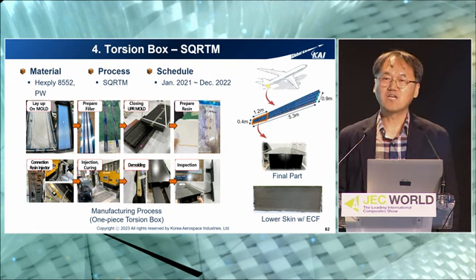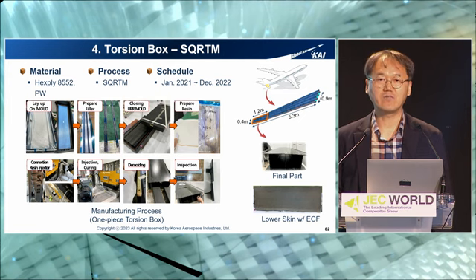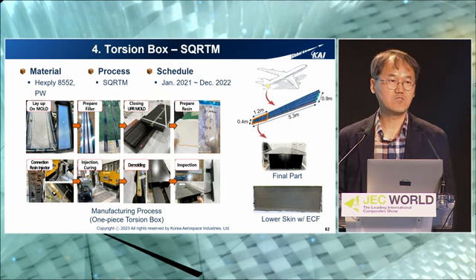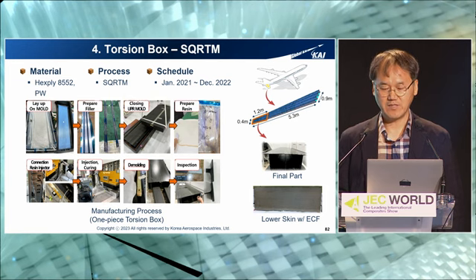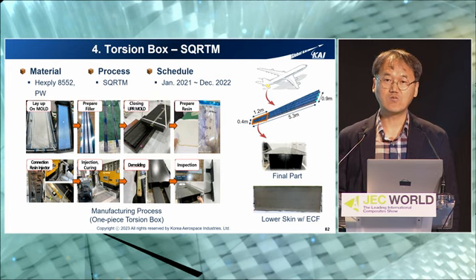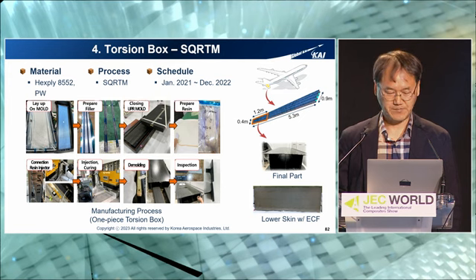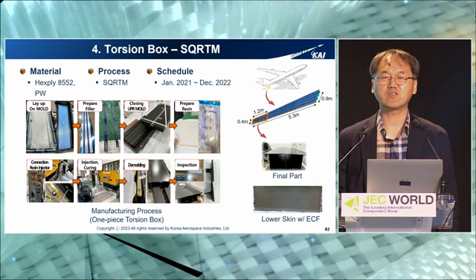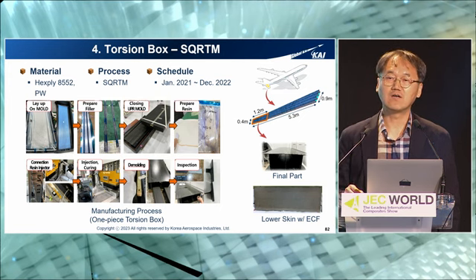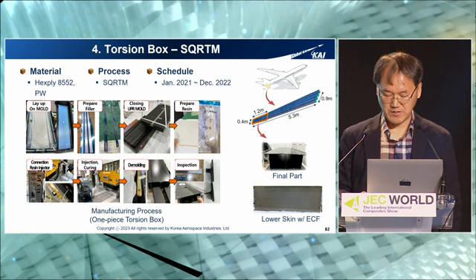This slide shows the SQRTM process. We selected Hexply 8552 prepreg material, which is a plain weave system. We demonstrated 1.2 meter by 0.4 meter demonstration parts, and also we applied expanded copper foil to protect against lightning strike. This is also a one-piece torsion box. We conducted every mechanical and physical test after completing the parts and during the parts manufacturing process window. And most of the outputs and results are within our expectations.